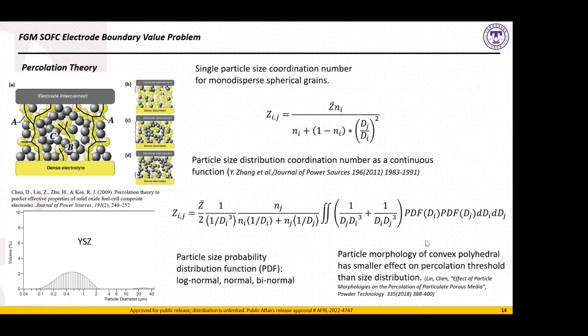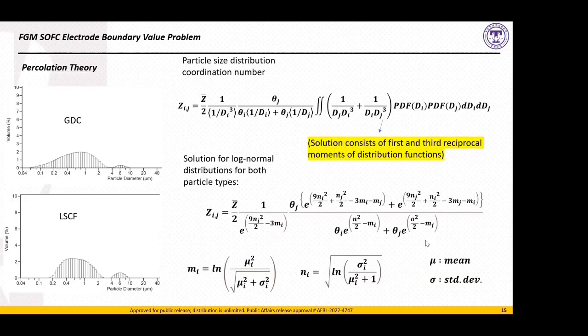This helps us because the solution to this integral formulation is not analytic if we have, say, a Gaussian distribution of grain sizes. If we have a log normal distribution, we can find an analytic solution. That was not found in the previous publication. This is a novel solution that we have formed here. This is the analytic integral for spherical particles with a log normal distribution.